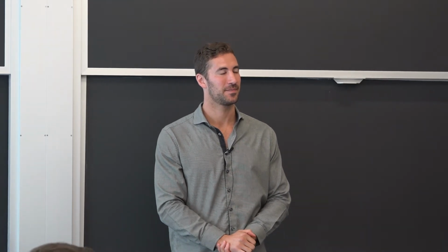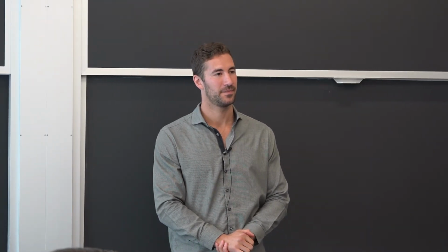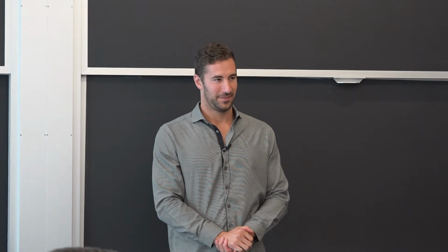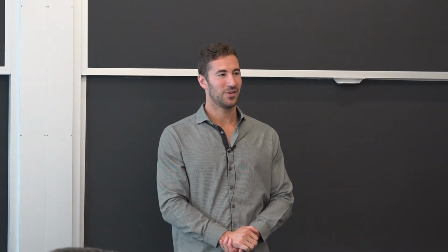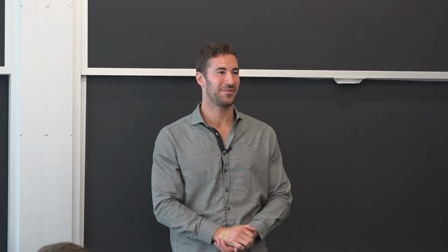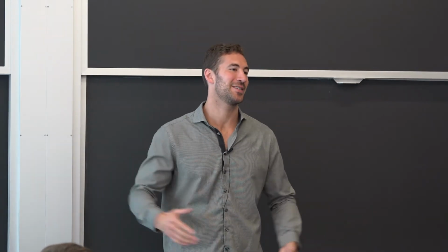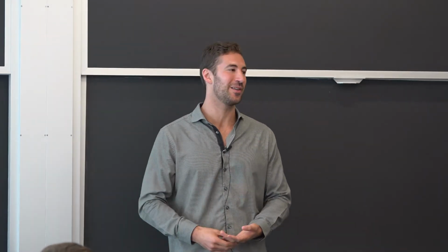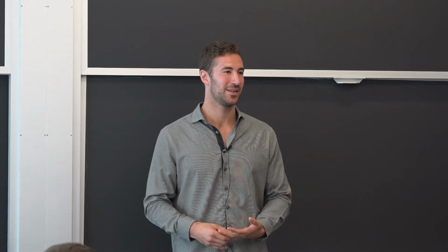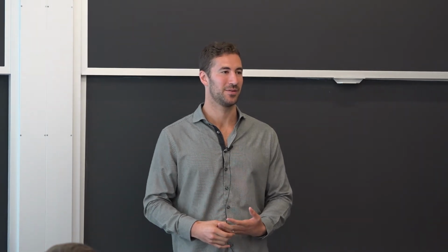Wouldn't it rip itself apart because of CTE mismatch? I mean, you're putting something really hot... The wrong geometry could, and a big enough temperature gradient could. But we're also making sure we're getting really good fusion between layers. And so that's a key part of it too.